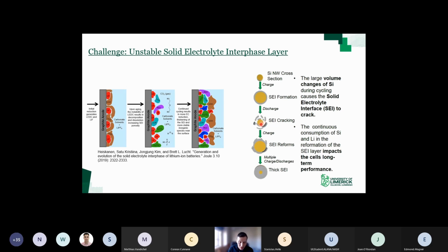For silicon, because you get the large volume expansion, you do get SEI formation, but it's not stable. Because the volume is expanding and contracting with every cycle, the SEI layer forms and cracks, and forms and cracks, and forms and cracks. That's very detrimental to the performance because you're getting continuous electrolyte decomposition, which is thickening the SEI layer, and that's increasing the impedance in the cell. So it does impact the cell's long-term performance. What we noted was that for germanium, the SEI layer was much more stable than it was for silicon.